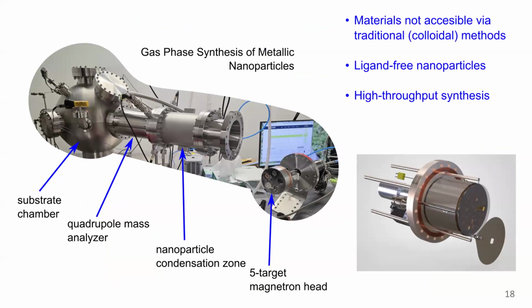It's not home built. We chose it because it's commercially available, and I believe it's also easier to control the sputtering as opposed to joule heating, because controlling the temperature of the target is harder compared to just controlling the current. You don't need to wait for it to heat up. You just press go and the plasma starts. It's a faster throughput.